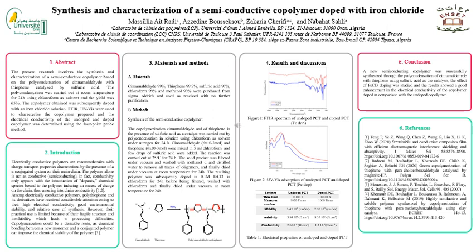The UV visible spectra of the copolymers show a higher absorption intensity for the doped copolymer in comparison with the undoped one. Both copolymers exhibit two main absorption bands. The first is in the range of 200 to 300 nanometers, which can be assigned to the π-π* transition, and the second in the range of 400 to 450 nanometers, which can be assigned to the band gap transition. The electrical conductivity measurement of both copolymers showed that doping polycinnamaldehyde-co-thiophene with iron chloride induced a significant improvement of the electrical conductivity.